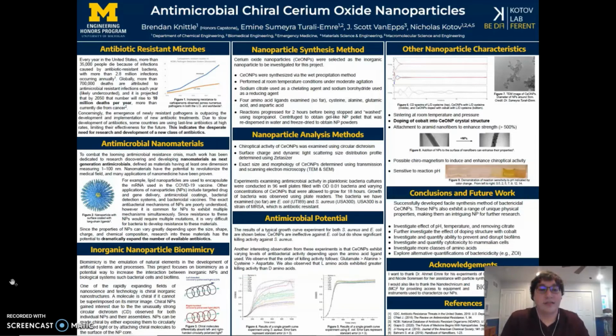Of particular importance is that on the right there, at a pH of 12, the reaction solution appears completely clear. This is before the addition of sodium borohydride, which normally is what we use to monodisperse and clear up the solution. So it's possible that if we react at a pH of 12, we might not need sodium borohydride in our reaction mixture. And that would be an interesting way to simplify our reaction and make it even easier.